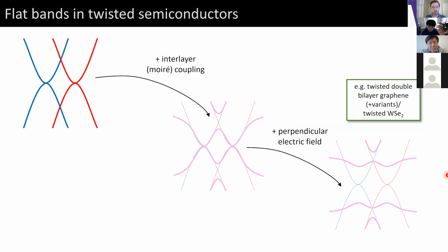All right, so as I mentioned at the beginning, twisting two bilayers gives us an extra tuning knob because now this system doesn't have this C2 rotation symmetry. So we don't have protected Dirac crossings at the neutrality point, and we can tune the bands as a consequence by modifying the gaps at the neutrality point with an electric field.